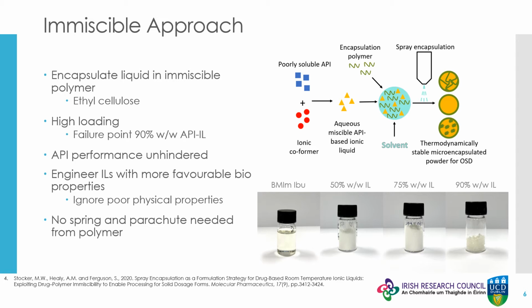From in vitro dissolution studies, we have found that the performance of the IL form of the drug is not impeded when combined with the polymer in this way, and so this allows us to design ILs with more regard to their in vivo performance without having to consider any detrimental physical properties that might result from this. As the polymer is phase separated from the IL and not interacting with it in any significant way, the performance improvements can be attributed solely to the drug being in the IL form.